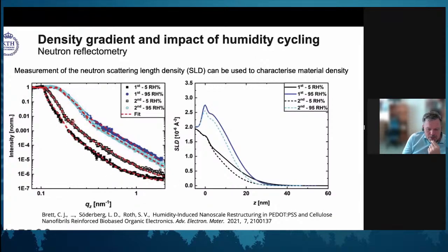So this QZ, which is the inverse, can be translated into the neutron scattering length density as a function of position in our film. What we can see in this case is that we can understand the effects of humidity cycling and see how that affects the density of the film. And by doing all of these things, we can separate water behavior from the dry structure. And then you can start to think about what is the effect of this.